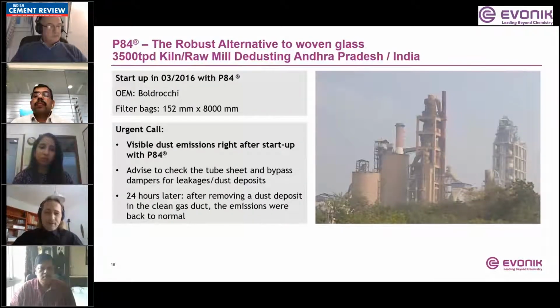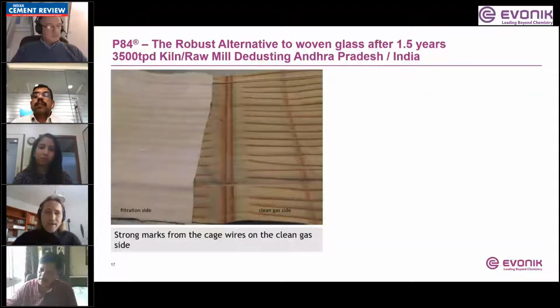24 hours later, there was no dust coming outside of the stack any longer. They found a dust deposit in the clean gas duct, removed it, and everything worked perfectly. After 1.5 years, we analyzed the used bag, and you see there are still orange imprints from the cage wires. There are still corroded cage wires, which created damage to the membrane bags. But within 1.5 years, none of the P84 bags showed any fatigue.